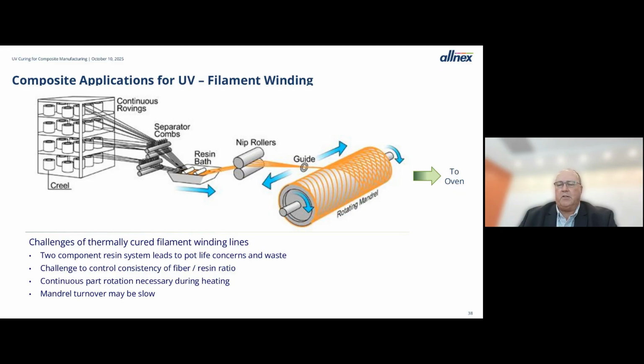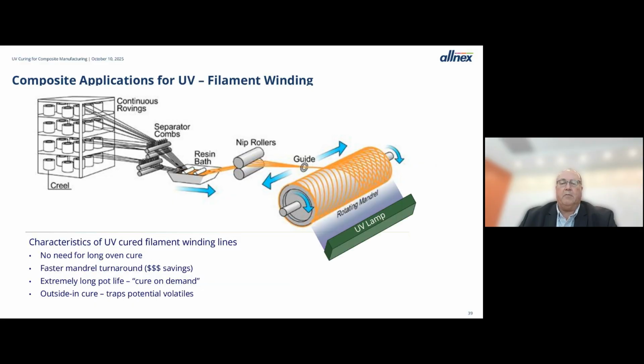When the layup process is done, that mandrel is removed to an oven where it's going to stay for hours, where it's got to be continually rotated, and that mandrel is now out of service for the entire cure process in that oven. If you switch to UV, the front end of the process stays the same. The fibers go through the resin bath, get saturated, laid up on the mandrel. But now when you've laid up your material, you flip on the lamp, cure in a couple of minutes.